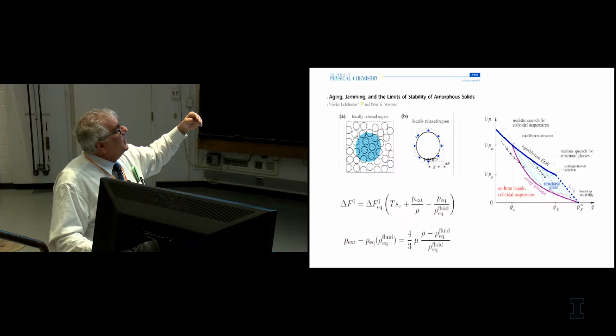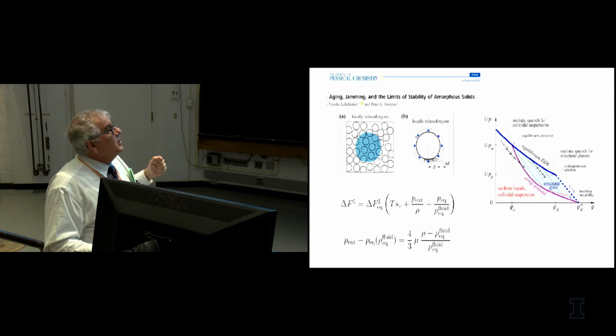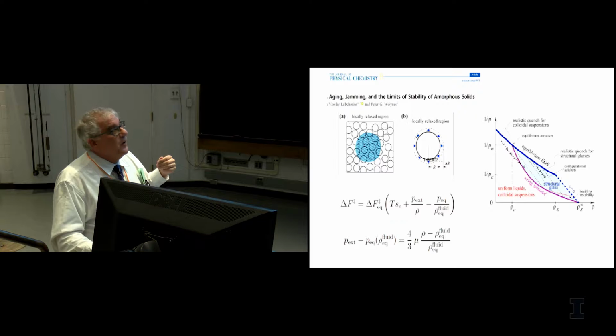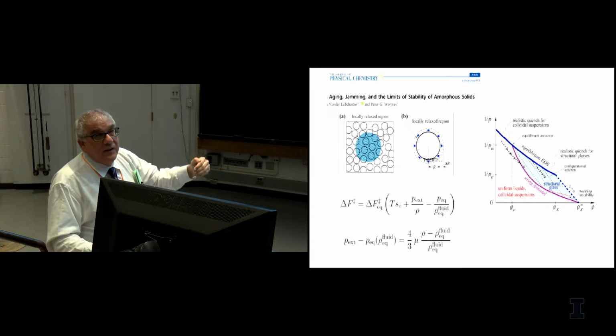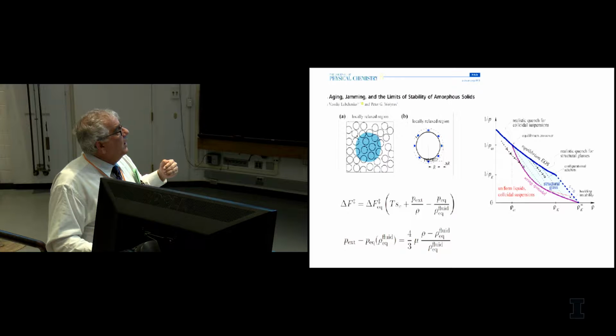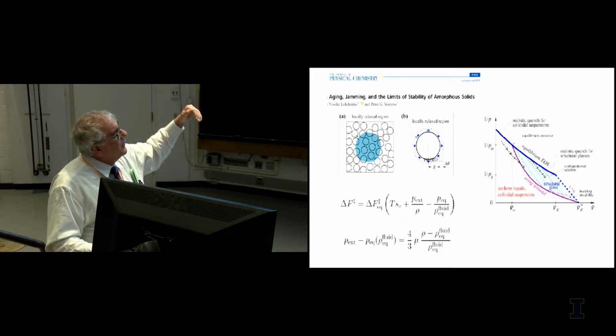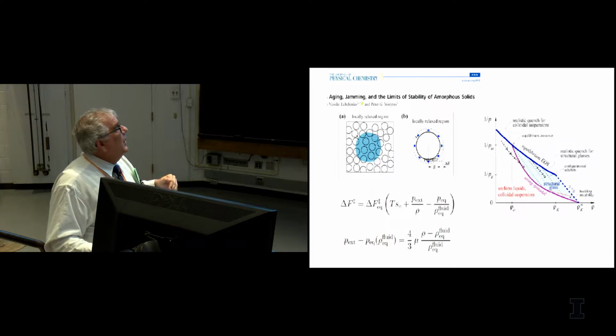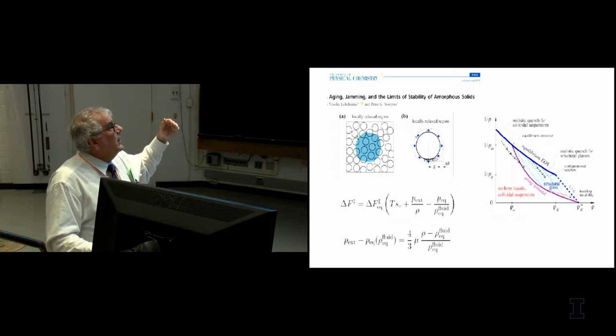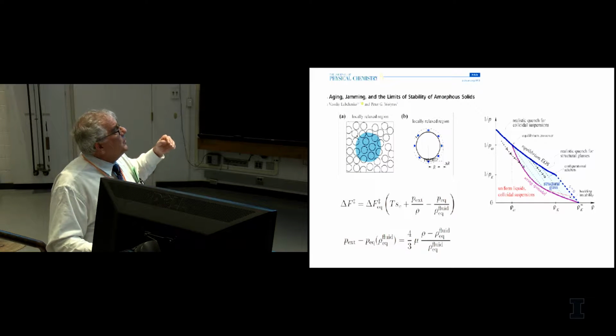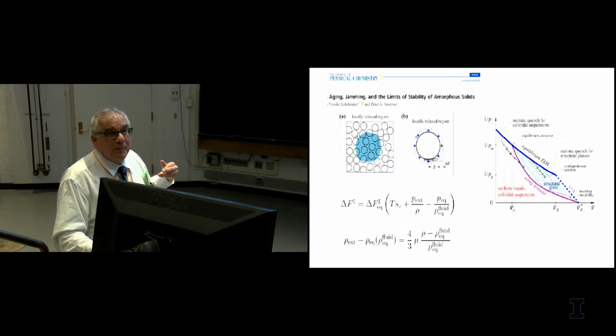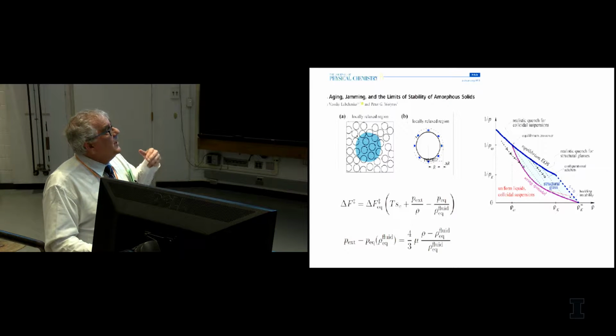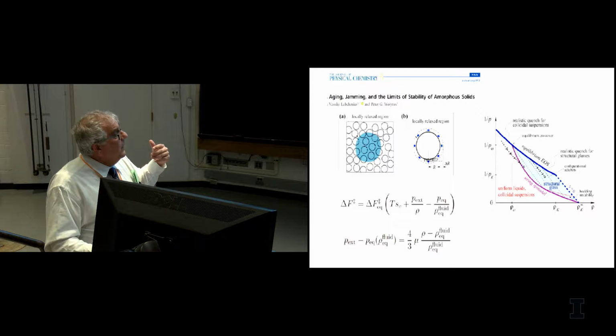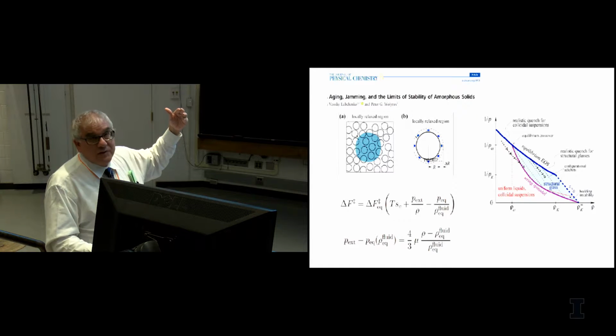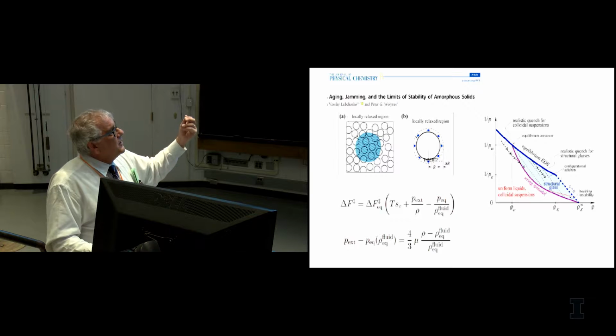What one finds then is that in addition to this instability point that was predicted on the equilibrium curve, that curve becomes extended as I allow the system to have very different pressures than the equilibrium pressure. And it allows us to have a spinodal that extends all the way down to infinite external pressure. Well, that corresponds to what's called a jammed system. And so the jamming system, again, in equilibrium theory, has been shown to be related to this spinodal point that we have here. This is kind of an extension of the theory.